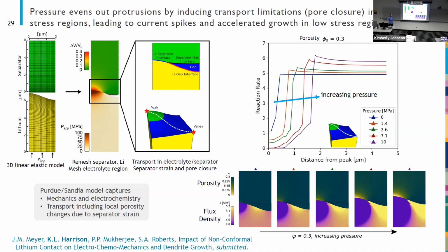But as we go out from that high pressure region, we will see a spike in the current because you have a constant current that you're applying. If you shut it down at some area, it has to be higher in other areas. And so this leads to plating in the areas of low pressure because you can't plate in the areas of high pressure. But it also leads to a lot of inhomogeneity in the current. And so this explains that we should see the protrusions sort of even themselves out because they're more likely to go to the low pressure regions if we shut down those pores. But it also means that we're going to have these current spikes.